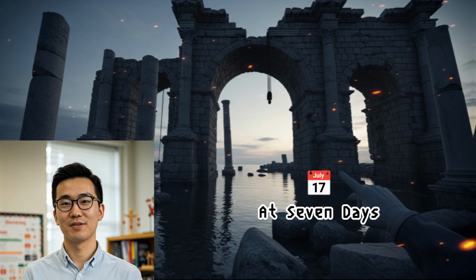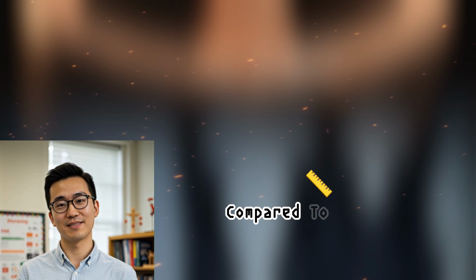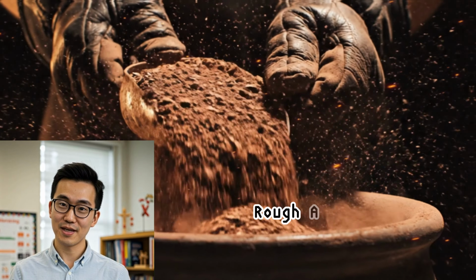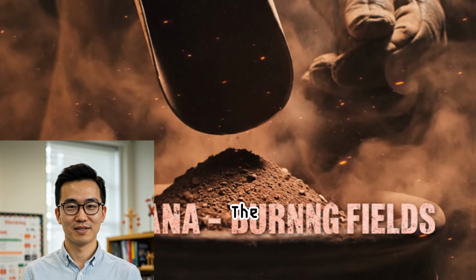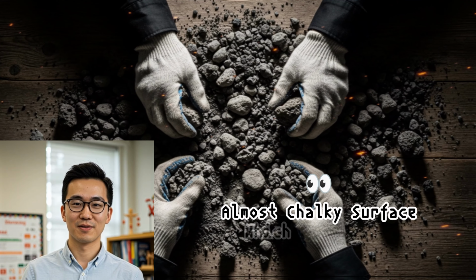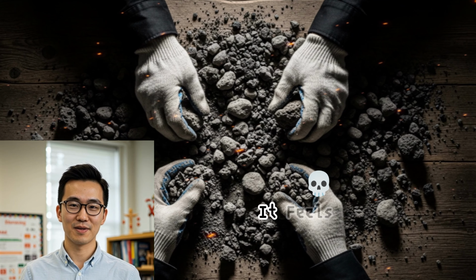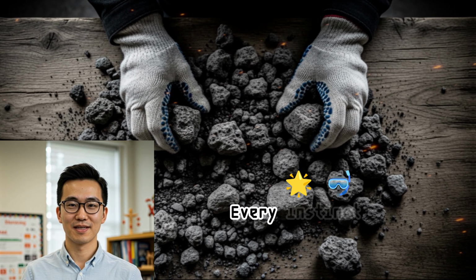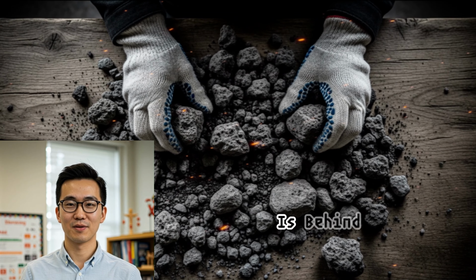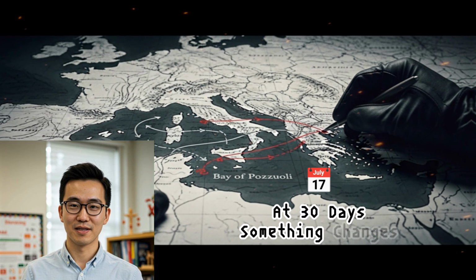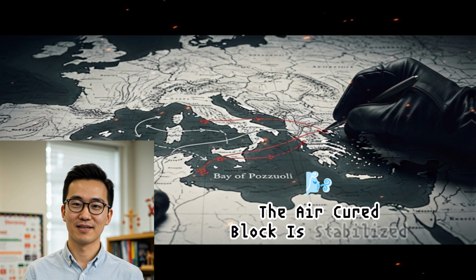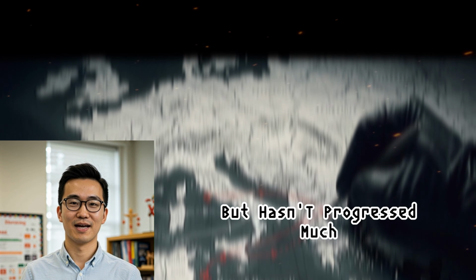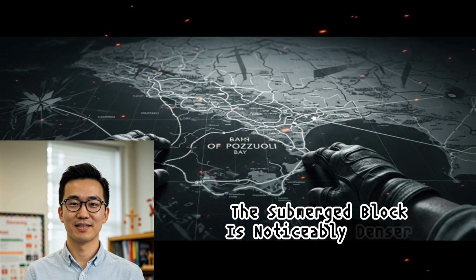At 7 days, both blocks feel underdense compared to standard concrete. Rough, a little crumbly at the edges. The air-cured block is harder. The submerged block still has a slightly soft, almost chalky surface, which looks like failure. It feels like failure. Every instinct says the underwater block is behind. At 30 days, something changes. The air-cured block has stabilized but hasn't progressed much. The submerged block is noticeably denser.